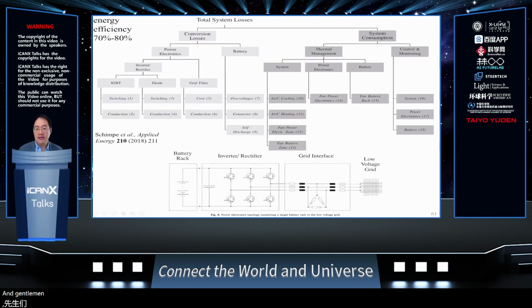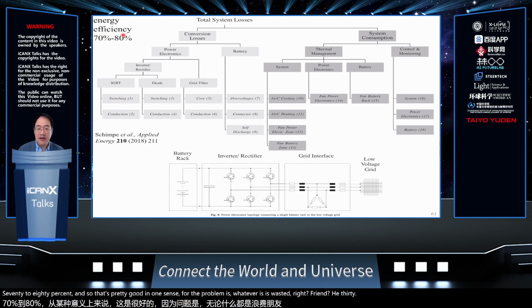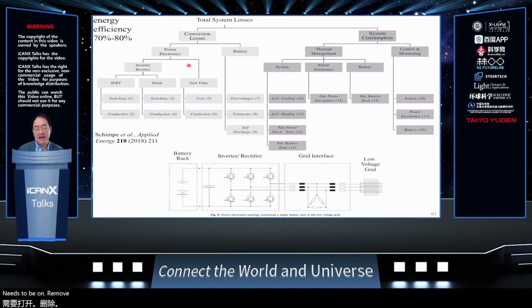And generally, this is the system layout of that grid-scale storage. And what is interesting is that the overall energy efficiency is 70 to 80%. And so that's pretty good in one sense. But the problem is whatever is wasted, right, 20, 30%, needs to be removed as heat. And that thermal management problem is really acute when you have a big battery. So the bigger the system, the more complex the system, the more dangerous it is. So in fact, sometimes the accident didn't start from the battery cell, it actually started from the cabling, from the electrical interfaces, from the power electronics.